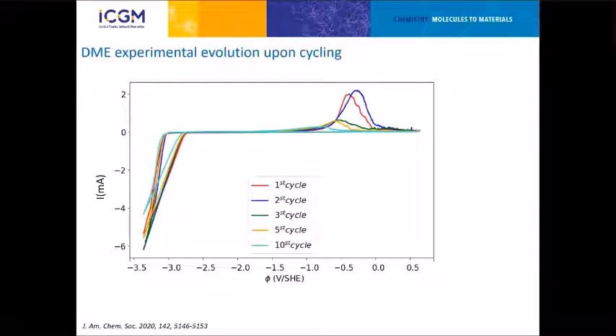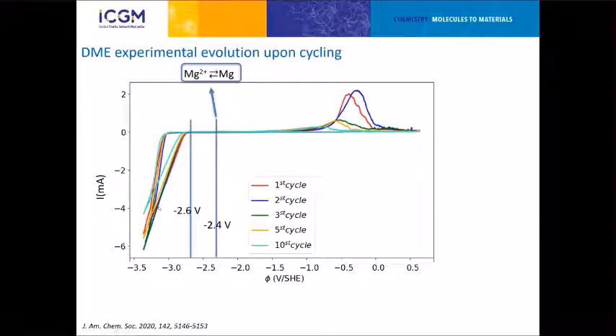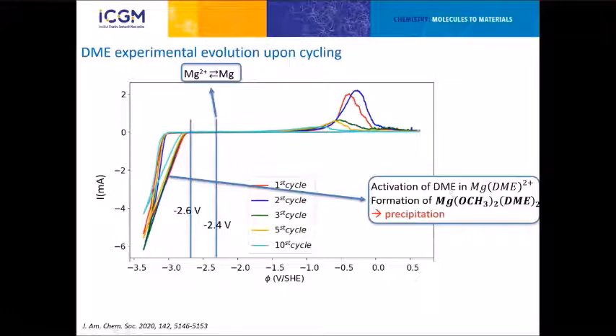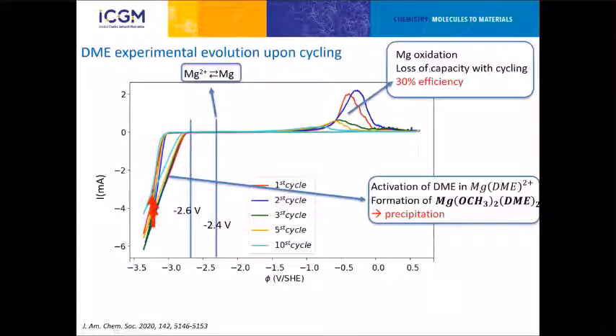If we look at the experimental results, I've said there's a magnesium reduction. And what we see, if we look at the zone where our solvents coordinated to magnesium start to be unstable, is that some kind of reduction already happens. That is certainly a mixture of magnesium reduction but also of DME, and some kind of precipitation that is going to isolate the electrode, and we see a decrease of the intensity on cycling. In the oxidation part, we also see that the amount of oxidized magnesium is quite low in comparison to the amount that was formed, and we have very low efficiency, meaning that there's some kind of secondary reaction happening.